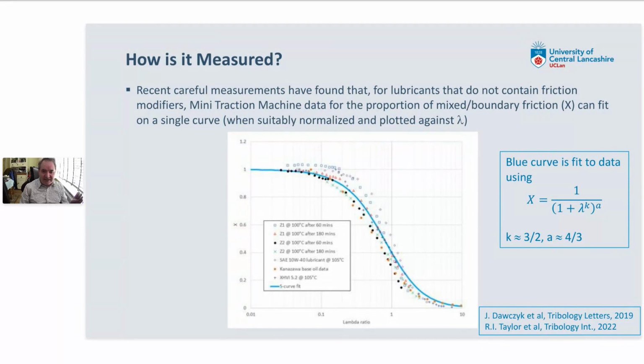Now, the mini traction machine has also been used recently by the Imperial College tribology group, and they did some interesting experiments where they tested a wide range of lubricants in the mini traction machine, and they subtracted the fluid film friction, and they normalized the data so that the boundary friction was normalized to 1. Crucially, they plotted the data not against speed, as is usually done in the mini traction machine, but against the lambda ratio. They actually found that you could find a common curve for a lot of the lubricants that were tested. I should say none of these lubricants had friction modifiers in, but this work suggested that you could come up with fairly simple equations to predict the proportion of mixed and boundary friction, which in this case we called X, as a function of the lambda ratio.